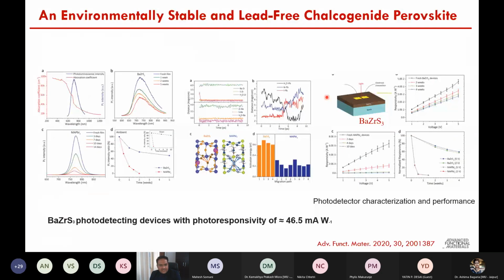And so they have to be environmentally stable. So BaZrS3 lies here. This is the work done by the RPI group, where they have shown how this BaZrS3 film actually shows stability towards the surrounding or the environmental effects. And they were able to show a very nice device on the photodetector characterization and performance. What they have shown is a photodetecting device with a photoresponsivity of around 46.5 milliampere per watt.